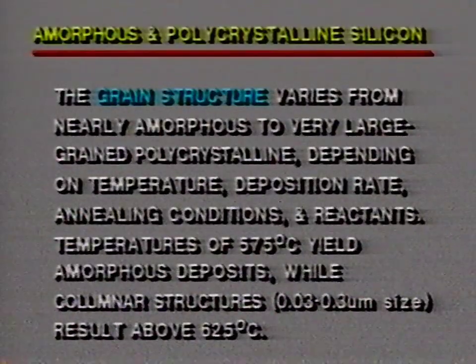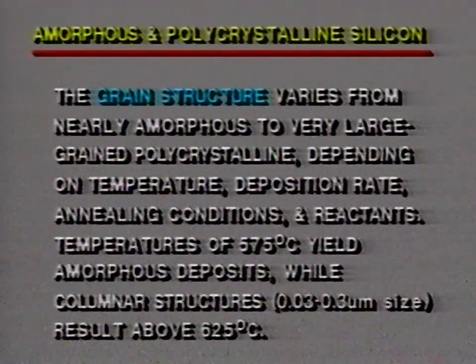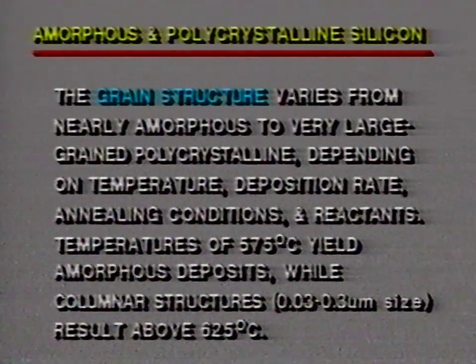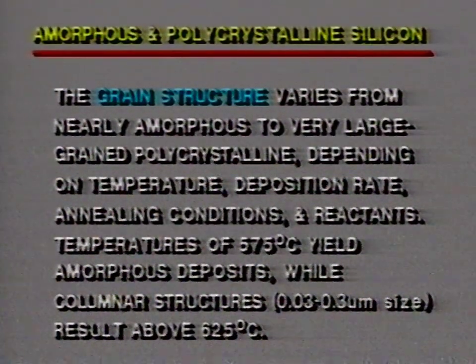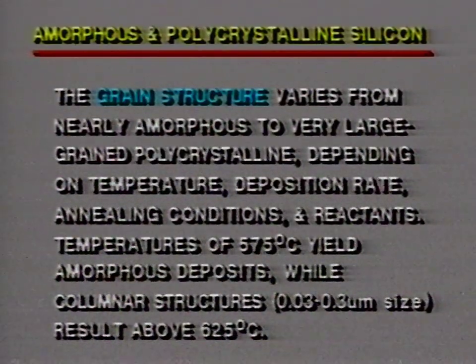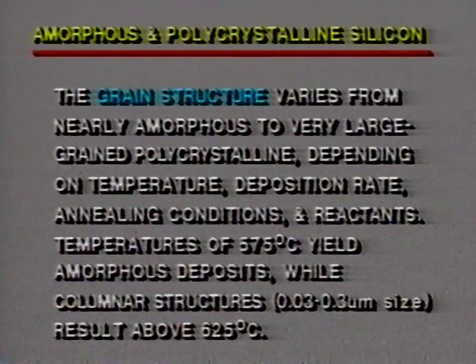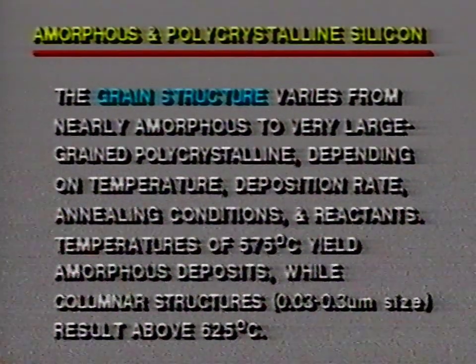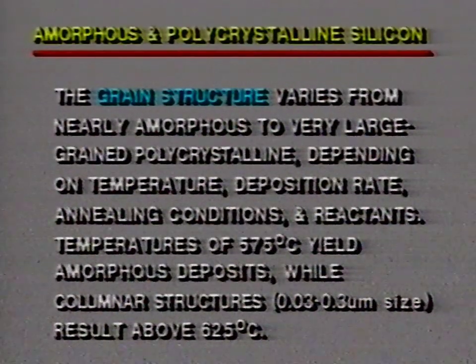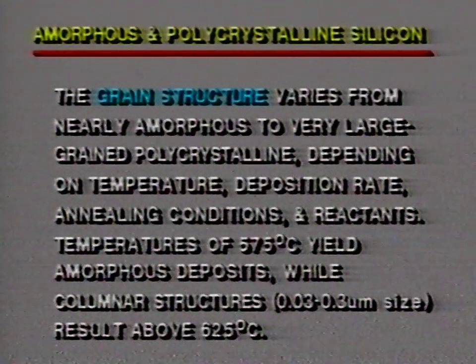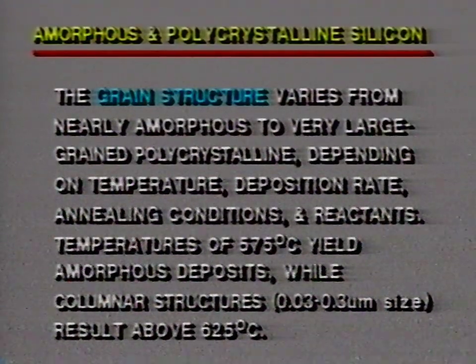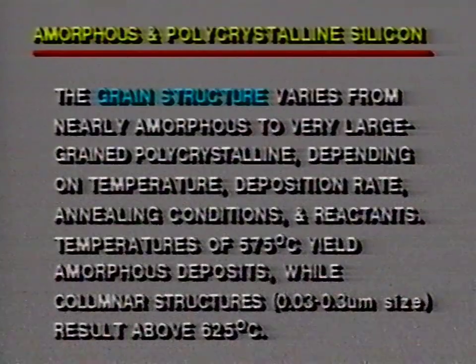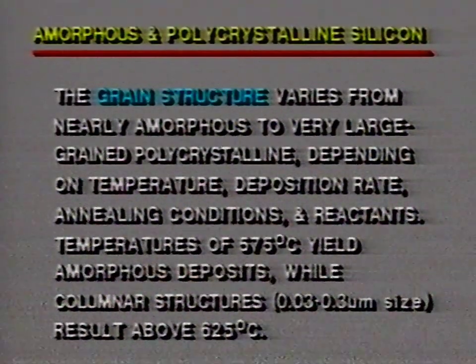Now, the grain structures of films deposited from silane vary from nearly amorphous to very large grained polycrystalline, depending on the temperature conditions, deposition rates, annealing conditions, and so on, and also the reactants. In general, a temperature less than 575 degrees centigrade yields an amorphous deposit, while columnar structures in the range of 0.03 to 0.3 micrometer sizes result at temperatures above 625 degrees C. So, as I said, the temperature is an extremely important aspect for forming specific types of silicon films here.